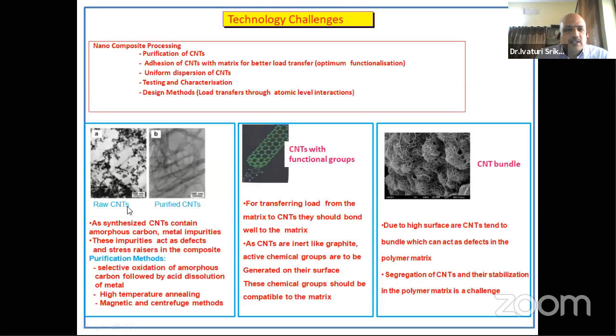There are different methods for synthesis of nanotubes. There is arc chamber synthesis and chemical vapor deposition based synthesis. Depending on the type of synthesis, you will have different degrees of impurities. Most of the impurities are either carbonaceous impurities, like amorphous carbon, or catalysts. Generally, catalysts are used, so iron, cobalt, nickel are general impurities. So metallic impurities as well as carbonaceous impurities are the general impurities in nanomaterials, carbon nanotubes especially.